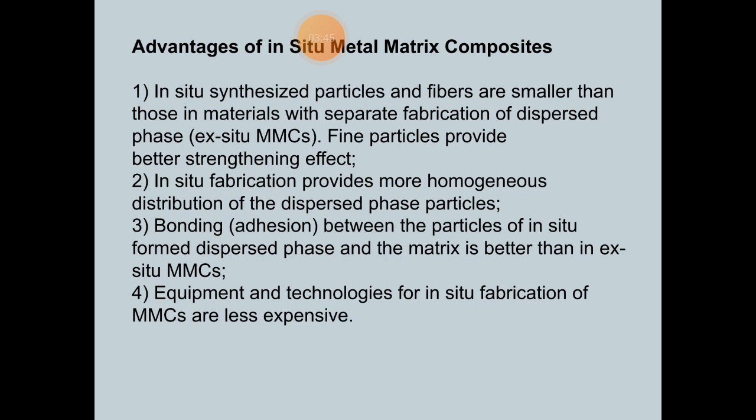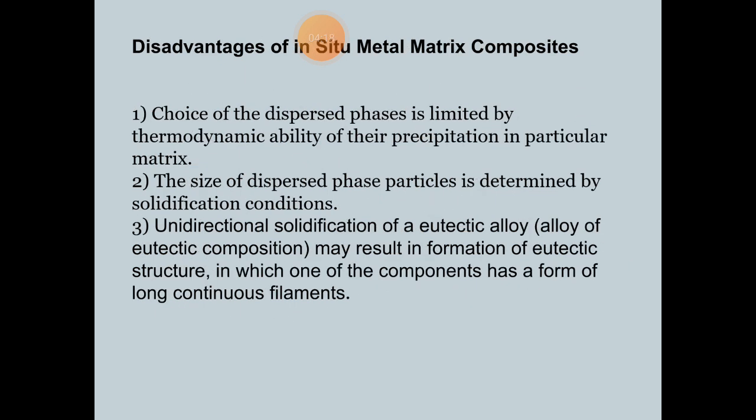Fine particles provide a better strengthening effect. Second, in-situ fabrication provides more homogeneous distribution of the dispersed phase particles. Third, bonding between the particles of the in-situ formed dispersed phase and the matrix is better than in ex-situ MMCs. Fourth, equipment and technologies for in-situ fabrication of MMCs are less expensive. Regarding disadvantages, the first is that the choice of dispersed phase is limited by the thermodynamic ability of their precipitation in a particular matrix.